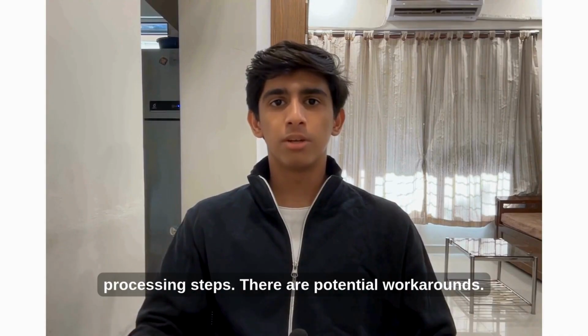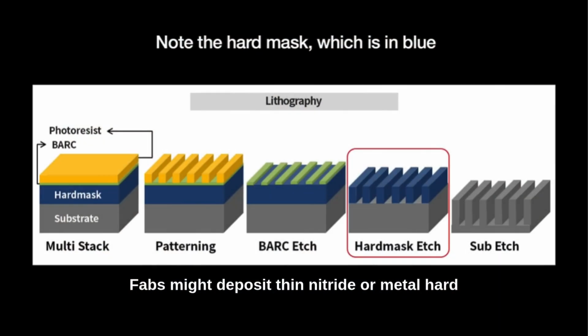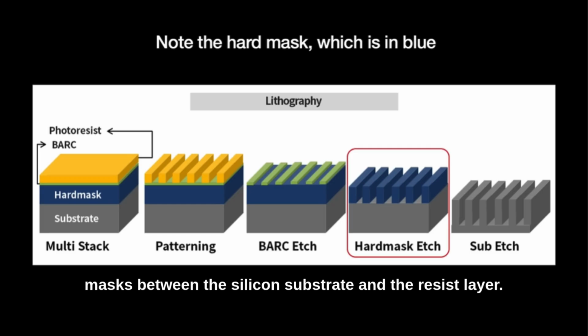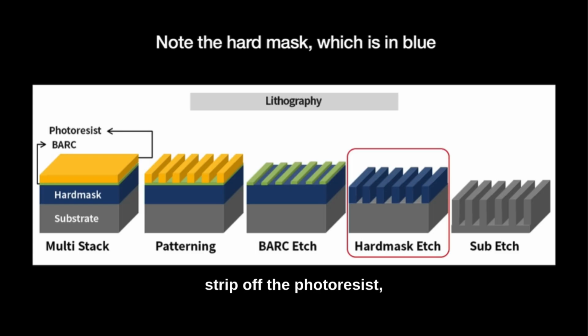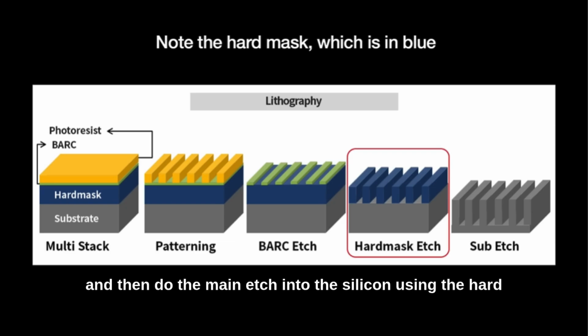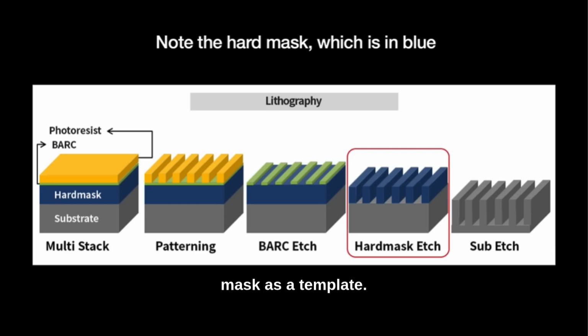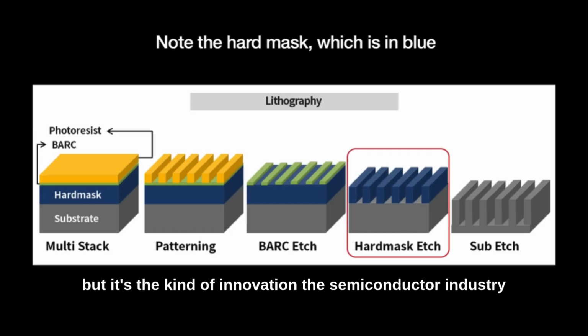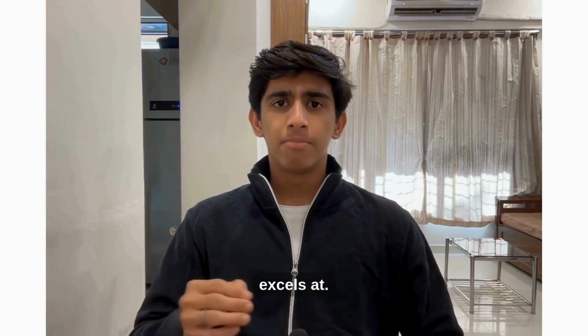There are potential workarounds. Fabs might deposit thin nitride or metal hard masks between the silicon substrate and the resist layer. You would do a preliminary etch into the hard mask, strip off the photoresist, and then do the main etch into the silicon using the hard mask as a template. This adds process complexity and cost, but it's the kind of innovation the semiconductor industry excels at.